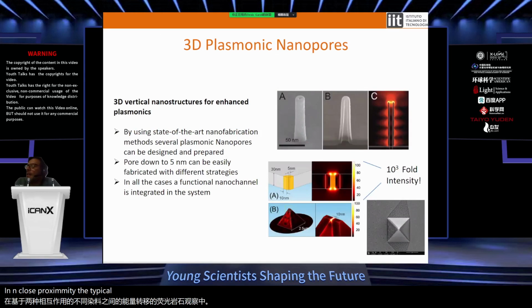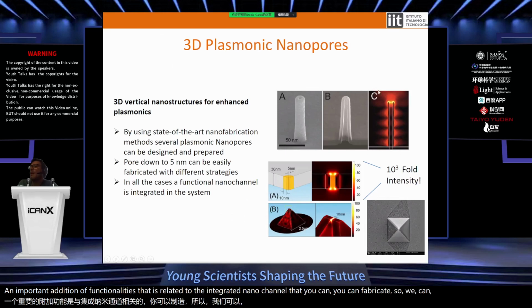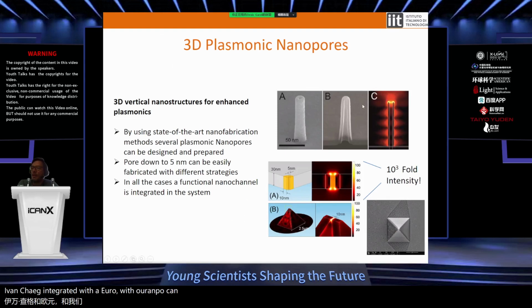The typical design of our nanopores is represented in these figures, and we are playing with this 3D configuration because it gives us important additional functionalities related to the integrated nanochannel that you can fabricate. So we can have a nanochannel integrated with our nanopore. It can have some enhancement at the aperture, but we can fabricate this object with different geometries in order to play a lot with the field.